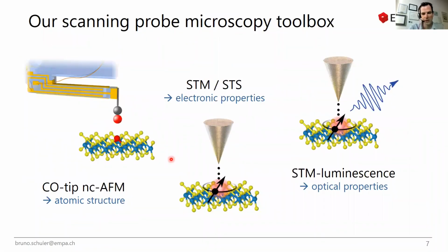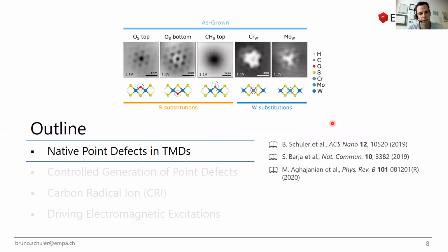So we looked into these materials with different scanning probe methods, and I think I don't need to go into too much detail what they are in this audience. So we used CO-tip AFM imaging to look at which atomic sites these defects are located, essentially, and then STM and scanning tunneling spectroscopy to look at the defect states to really map out the defect orbitals, and then STM luminescence as a third technique to further investigate optical properties of individual defects. So these are the things we are talking about during the talk.